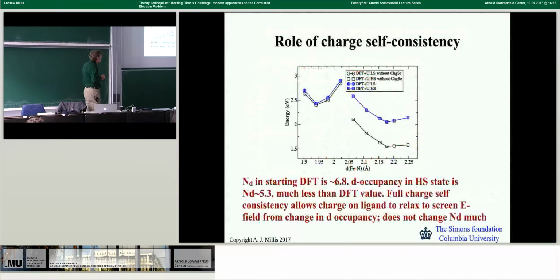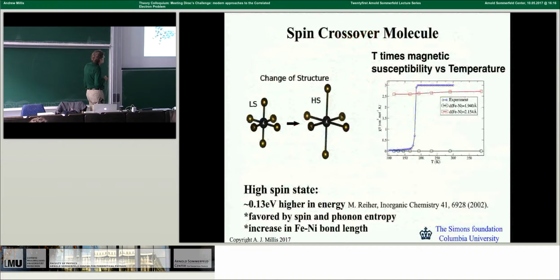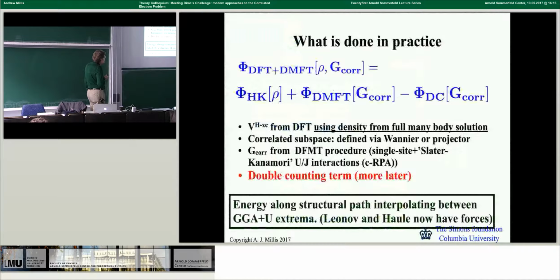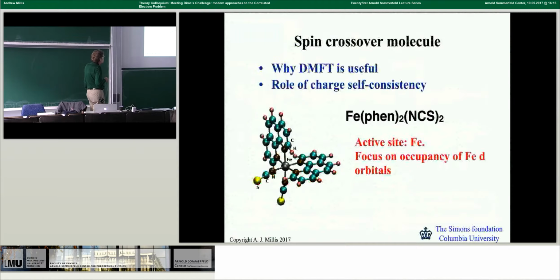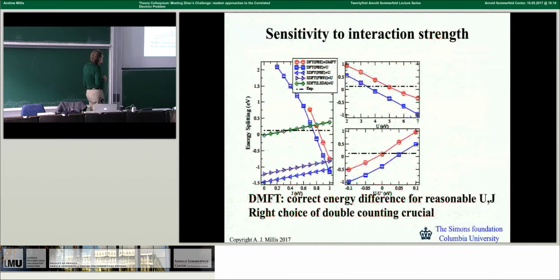Here's what's bad. When we solve this impurity problem, this DMFT problem, we have to choose an interaction on the correlated site. There are various ways to choose it, but you may ask, how does the answer you get depend on the value of the interaction and the double counting you choose? What you find is that the critical value of the energy difference between the high spin and low spin state, just focus on these. These lines have to do with density functional theories, which are just terrible. Focus on this. What you see is that the answer you get depends very sensitively on the Hund's coupling you choose. What you see here, even worse, is that the answer you get depends very sensitively on the double counting contribution that you choose.